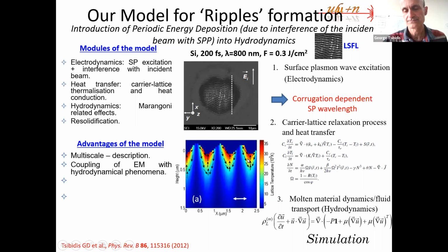Yes. So is it possible, let's say, also experimentally, I don't know if this is important, to get this temperature and the deformation inside the material, not only the surface, but go in the depth? The problem with experiments is that you can see only the results. So you have to perform some AFM experiments to take some cross sections, so to break it and to see the actual height, because this is a SEM image, which is not representative of the height and the depth of the profile. I was thinking about tomography, to also get information about the depth. Is this important for the phenomenon, or not so much?